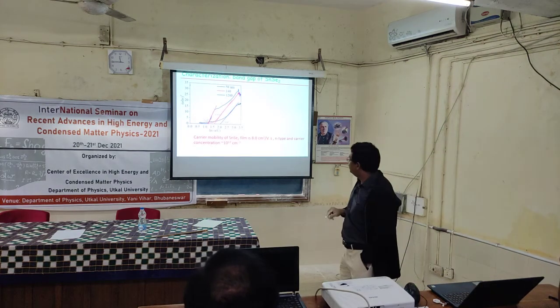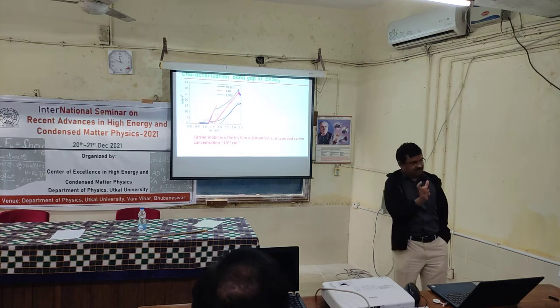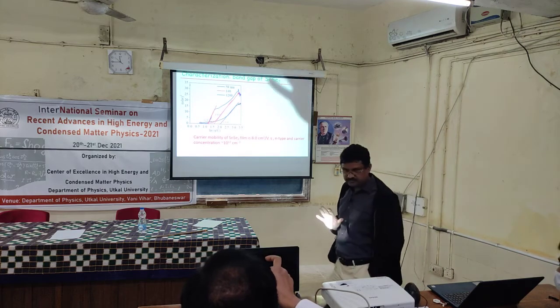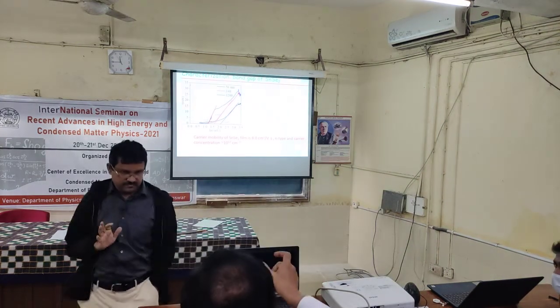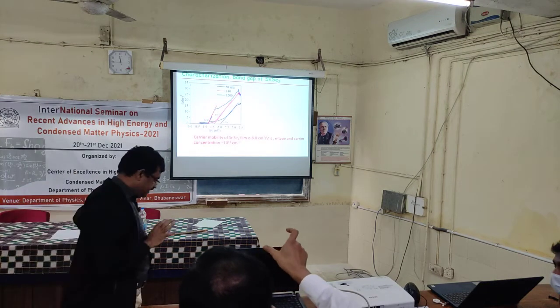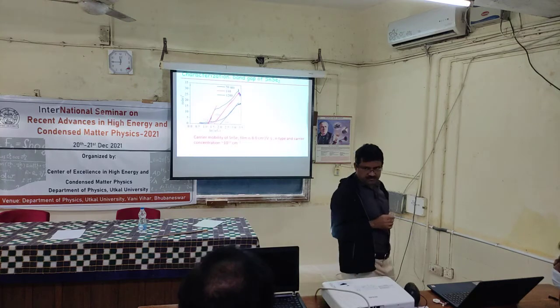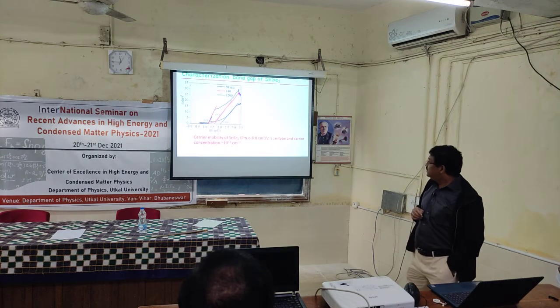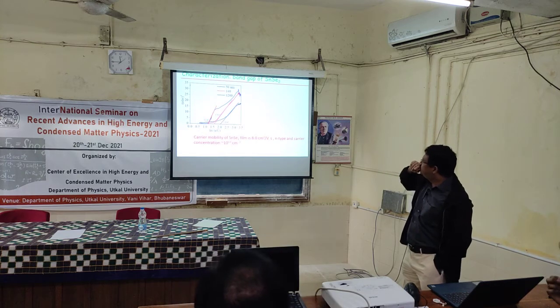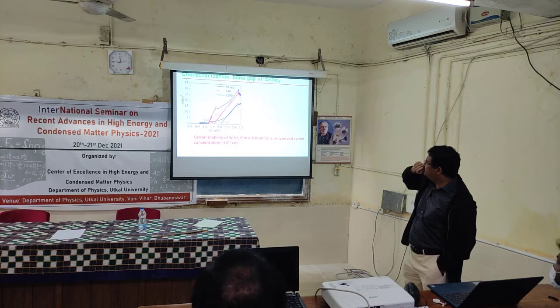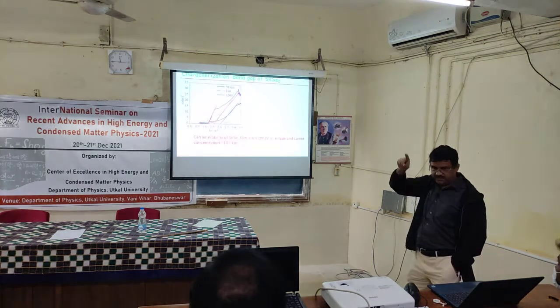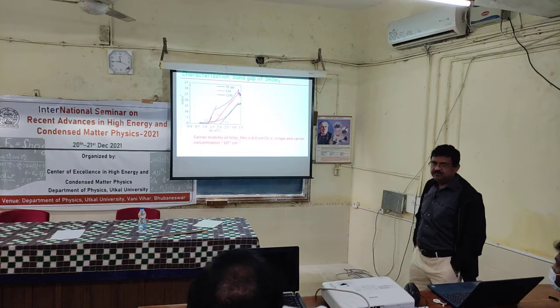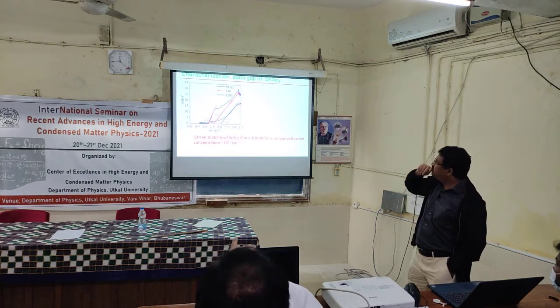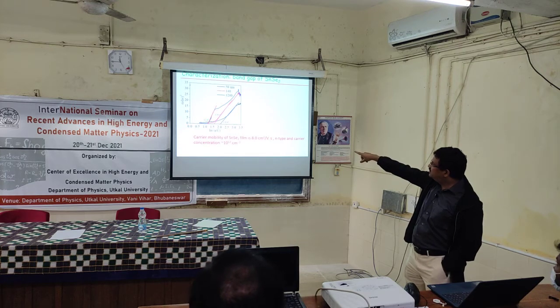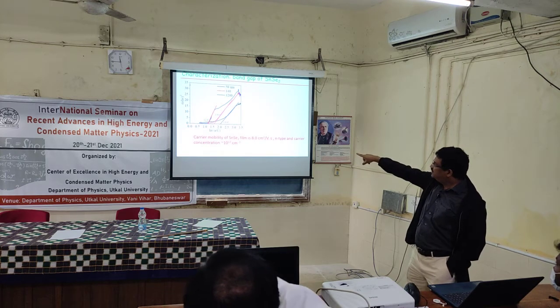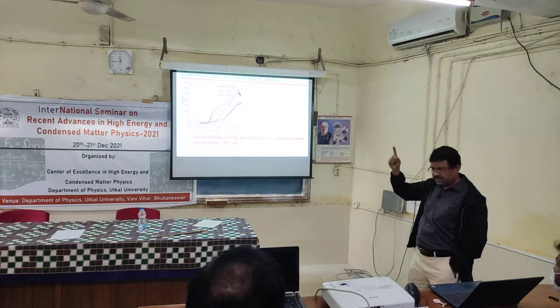So this is how it is. And of course, you can always get a plus minus. So it depends upon which range of h nu you are considering, and the corresponding linear region will define the linear fit, right? For example, the Tauc plot, if I am between say 2.5 to 3 eV, then you get the maximum if you plot the derivative. But can I fit a linear curve from say 1 to 2? It's also kind of linear. No, where we will get the maximum.